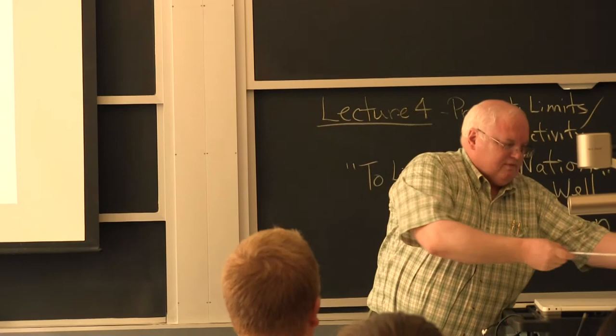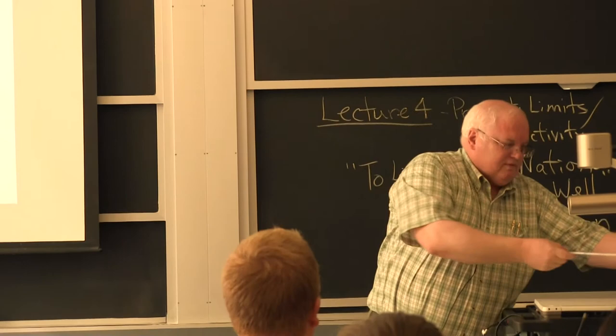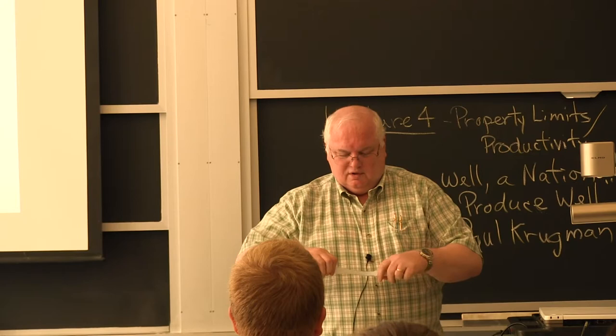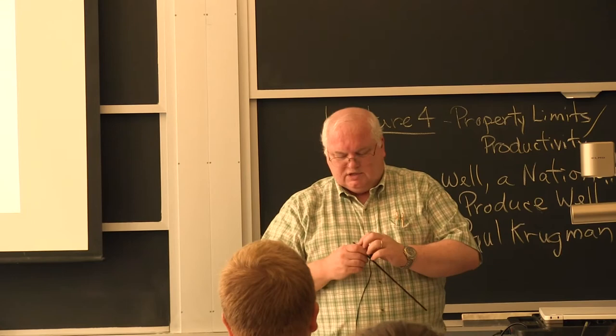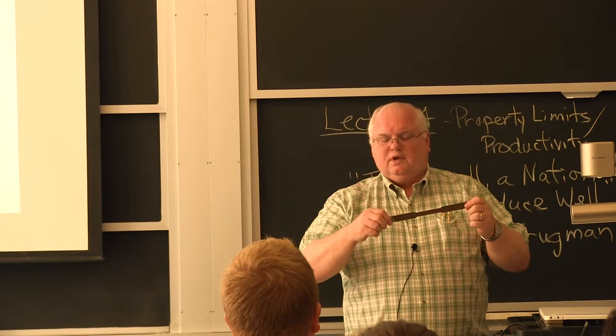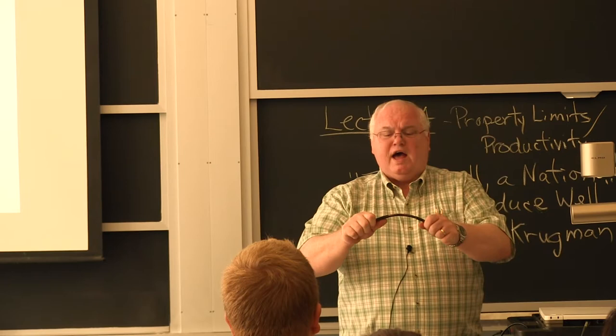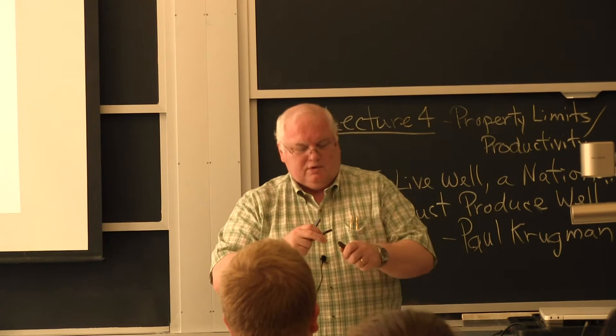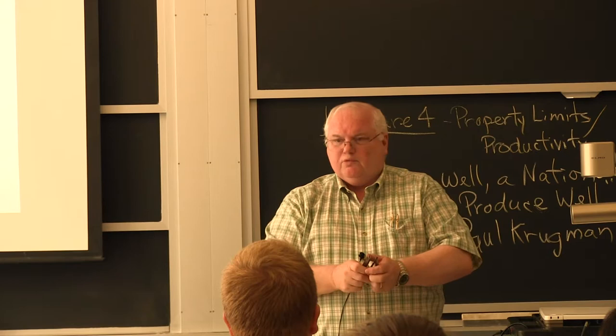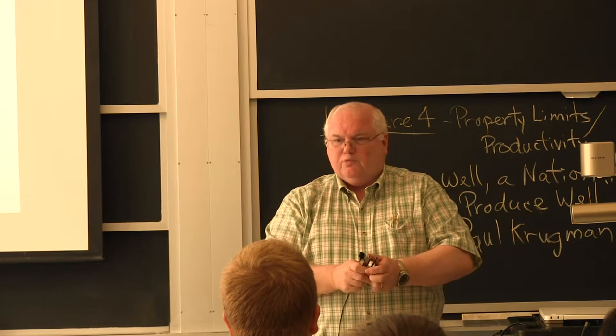Here's a demo of brittle versus ductile — both plastics. This one, polyethylene or polypropylene, I can bend all I want; it bends back mostly. If I keep doing it forever, it will eventually break in fatigue. This piece of polymethyl methacrylate — better known as plexiglass — if I break it, you can see a small shear lip on the compression side and a brittle fracture in between.